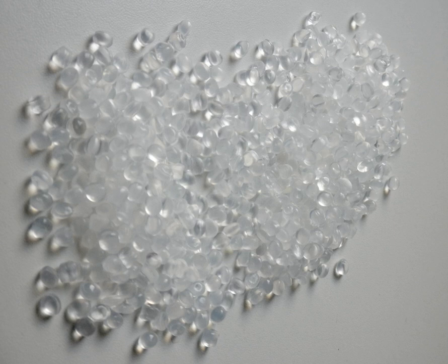Ethylene acrylic acid copolymers (EAA). Copolymers of ethylene and unsaturated carboxylic acids such as acrylic acid are characterized by good adhesion to different materials, by resistance to stress cracking and high flexibility. However, they are more sensitive to heat and oxidation than ethylene homopolymers. Ethylene acrylic acid copolymers are used as adhesion promoters. If salts of an unsaturated carboxylic acid are present in the polymer, thermo-reversible ion networks are formed, they are called ionomers. Ionomers are highly transparent thermoplastics which are characterized by high adhesion to metals, high abrasion resistance and high water absorption.